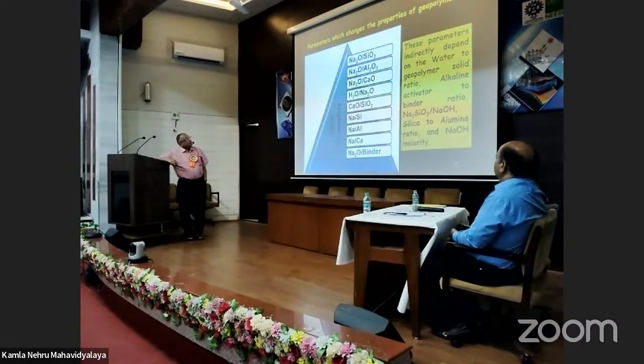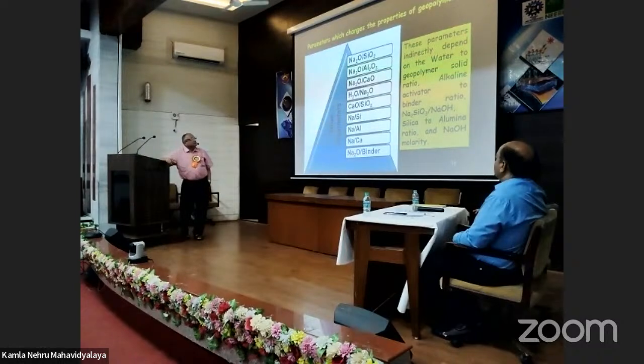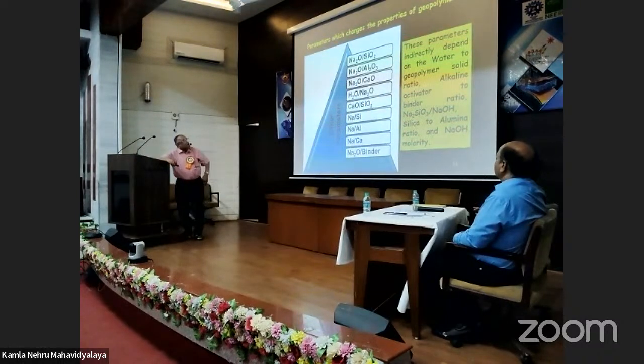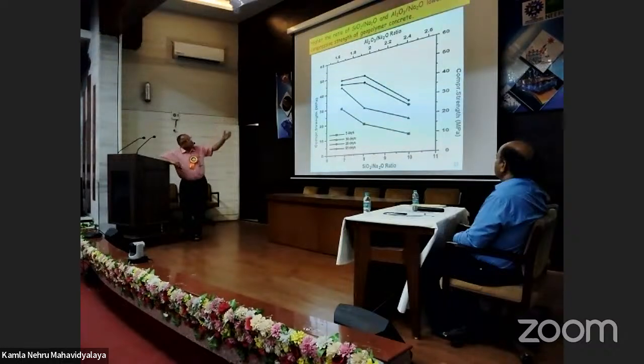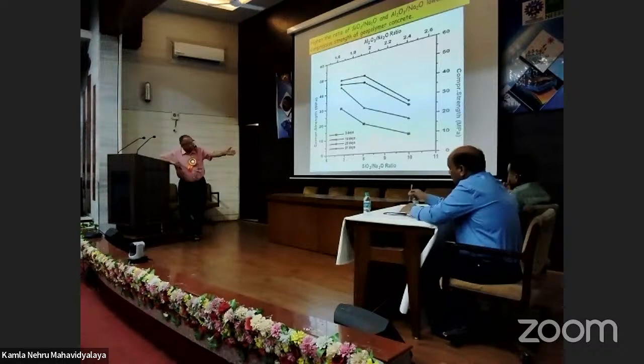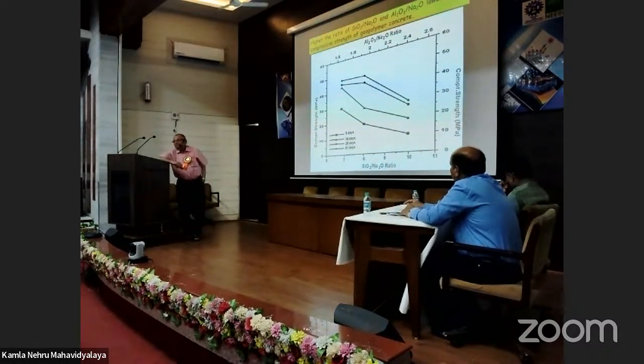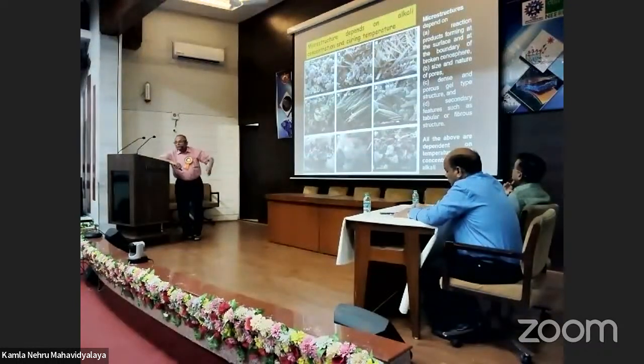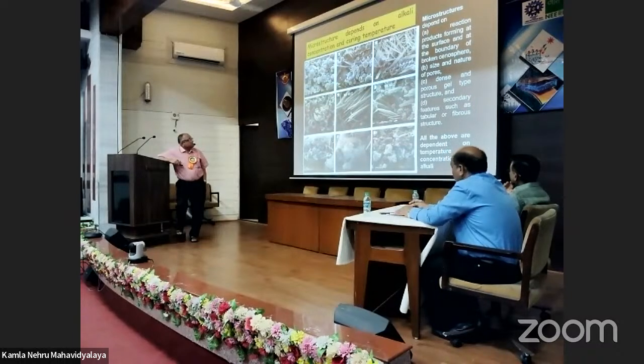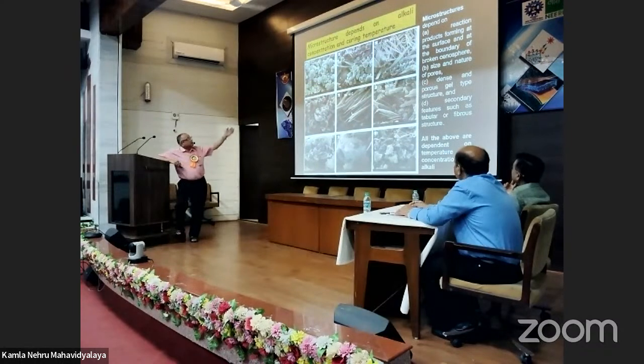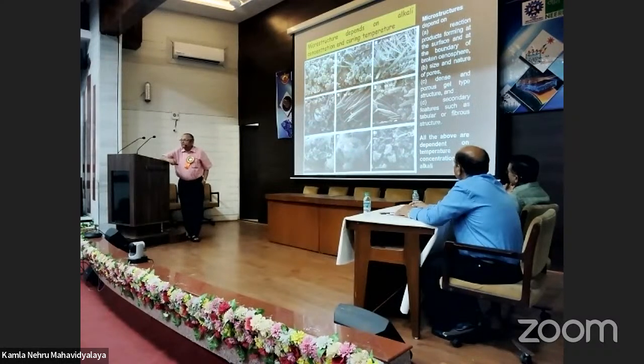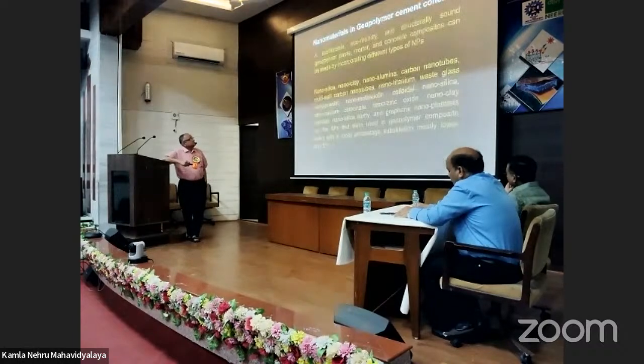These are the parameters which change the properties of geopolymer: sodium oxide silica ratio, sodium oxide alumina ratio, sodium oxide calcium oxide ratio, water sodium oxide ratio, and others. These parameters indirectly depend on the water to geopolymer solid ratio, alkaline activator to binder ratio, etc. Again, with the change of alumina sodium oxide ratio and silica sodium oxide ratio, if we increase it, the compressive strength decreases as a function of time. Also, with different temperature and different concentration, the morphology of the geopolymer, if you record it with the scanning electron microscope, also changes depending on the temperature, the raw material and the curing temperature.